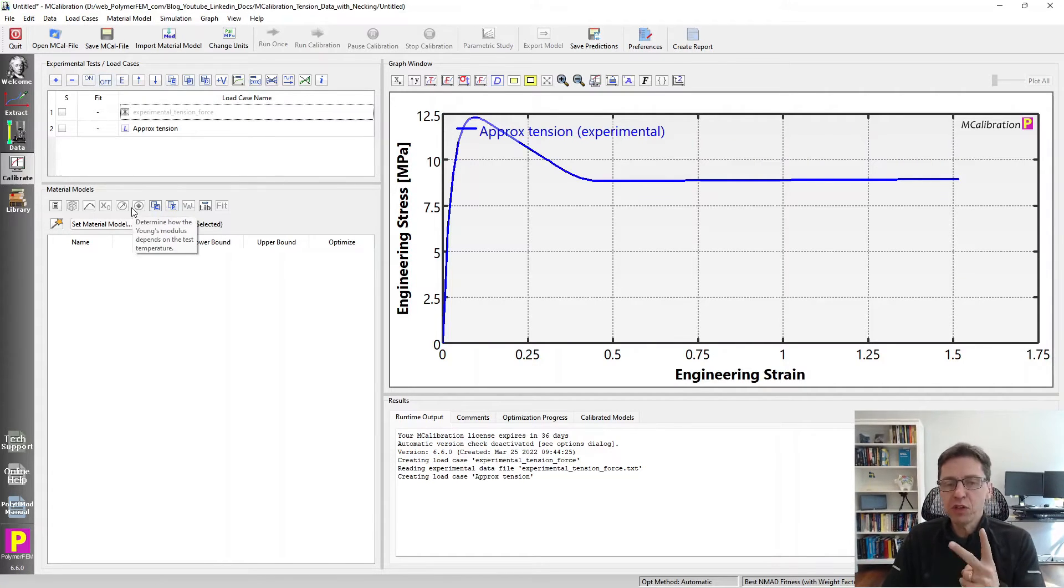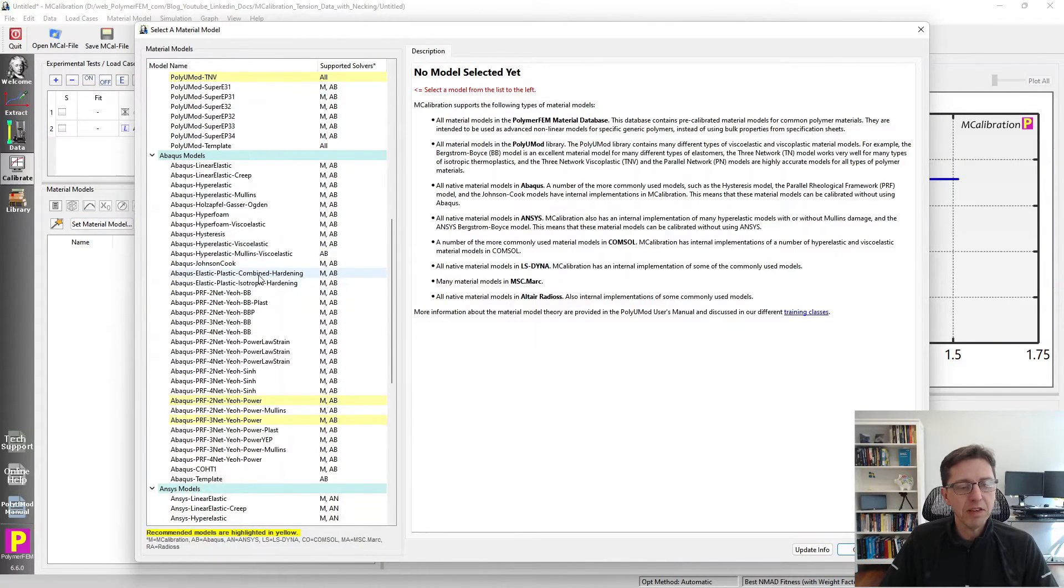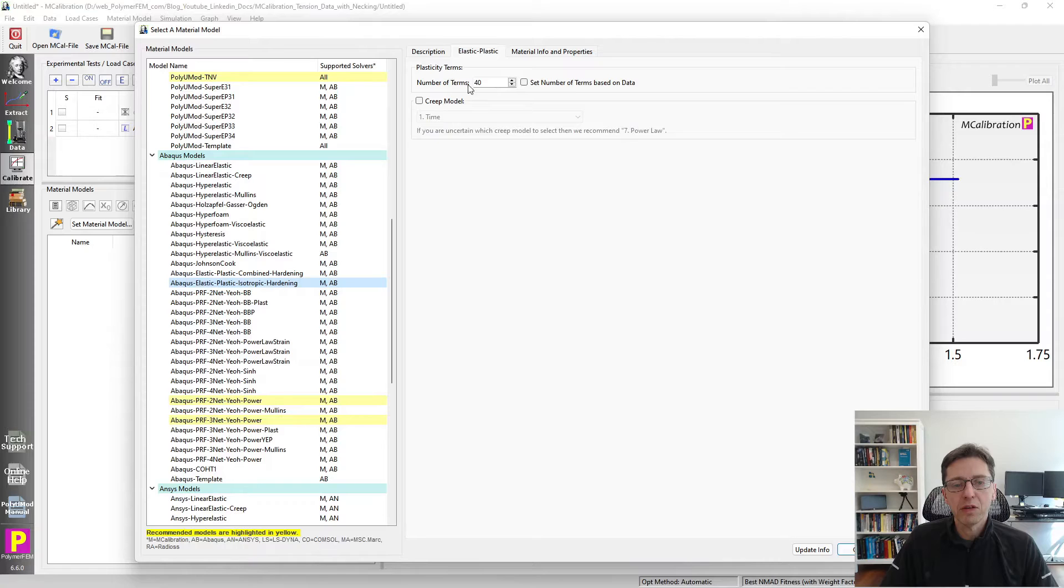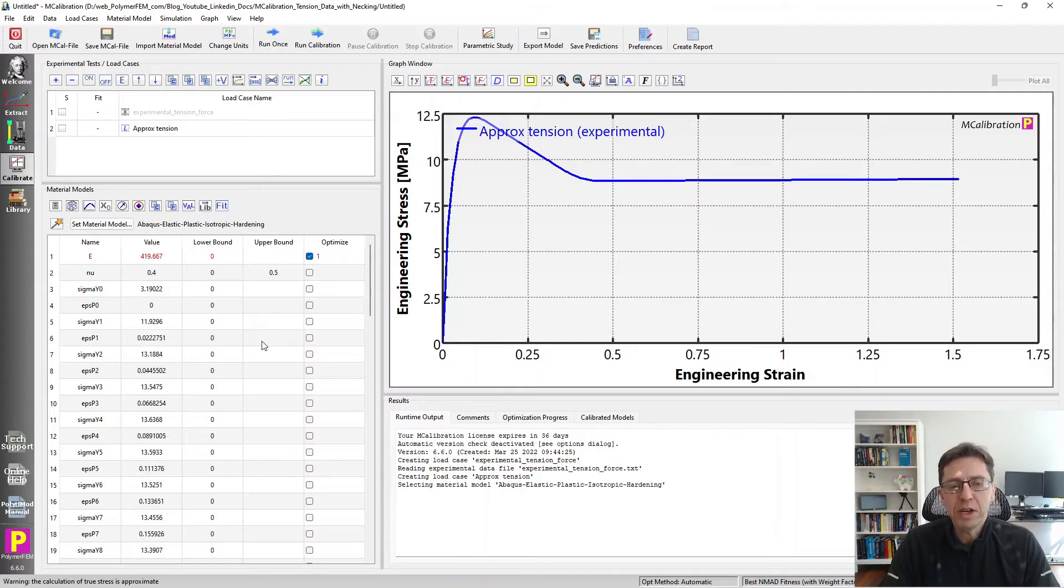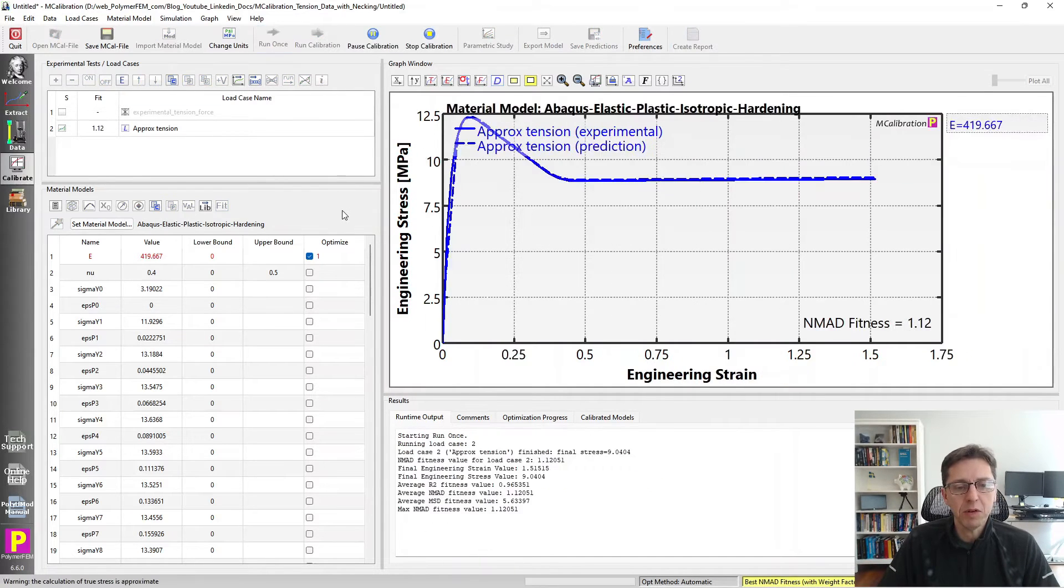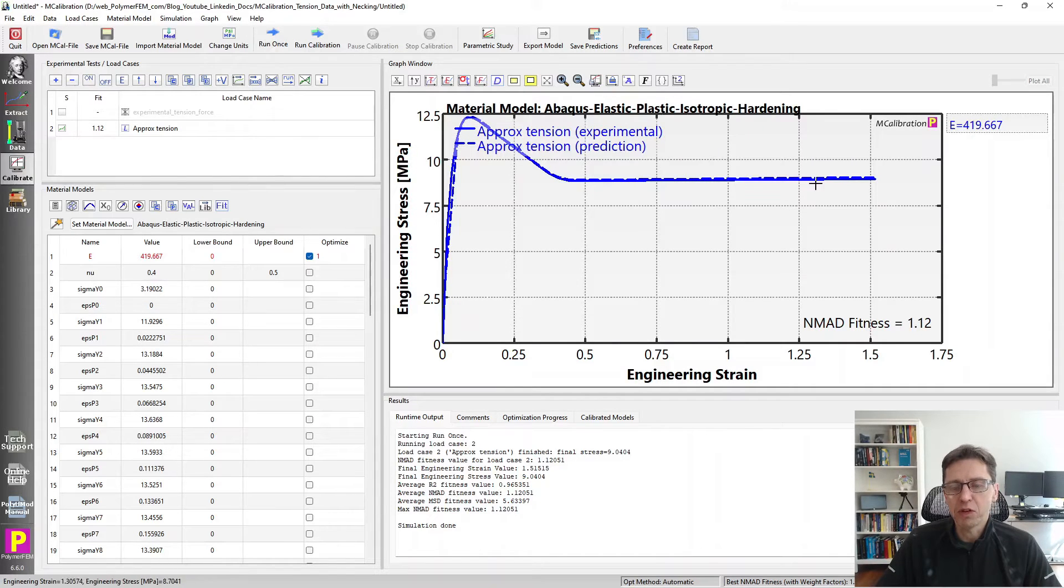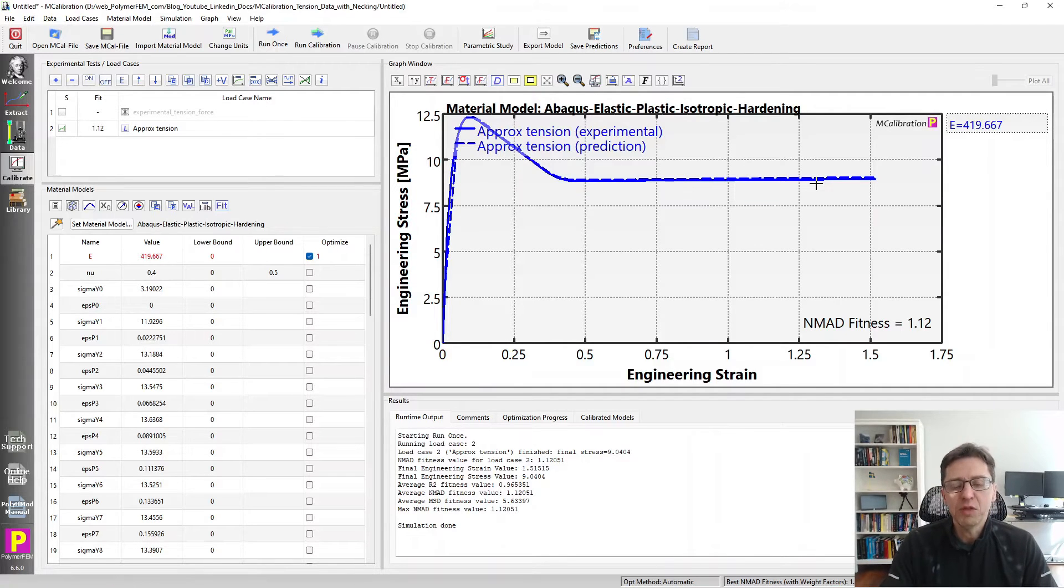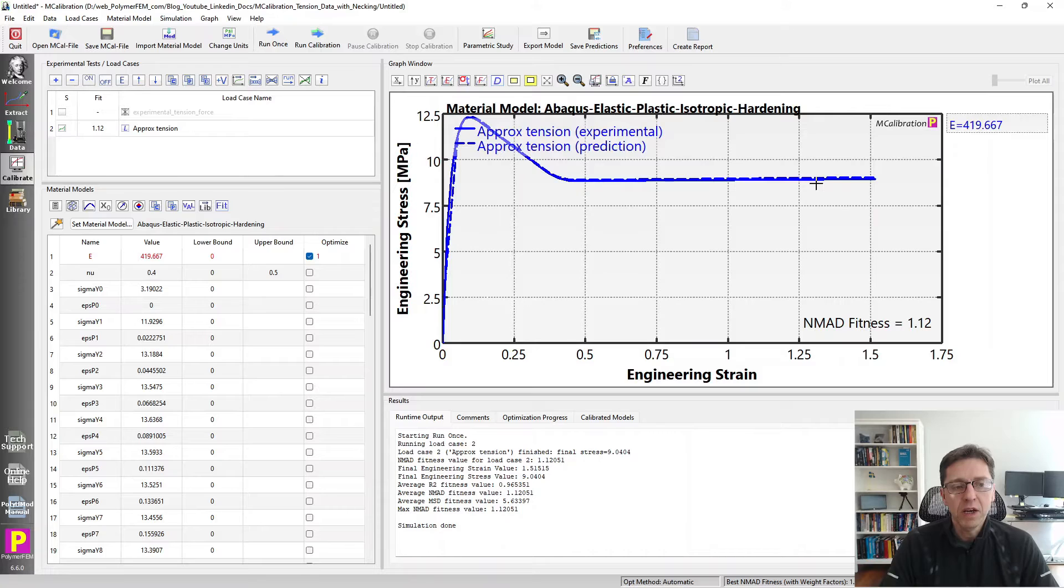I'm going to turn off the more advanced force displacement data. We're going to do pre-calibration to this data which will speed up this whole procedure a lot. I'm going to calibrate two different materials. I'm going to start with a very basic elastic plastic isotropic hardening material model that's in Abaqus. For this particular material model, MCalibration picks the parameters pretty well. The dashed line is pretty much on top of the solid line. This is because it's a piecewise linear model - it's very easy to calibrate. You don't actually have to search for the parameters.